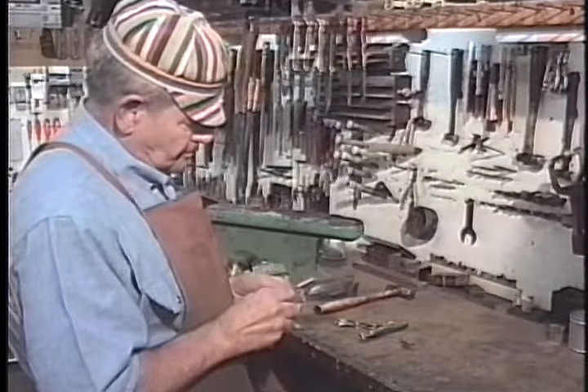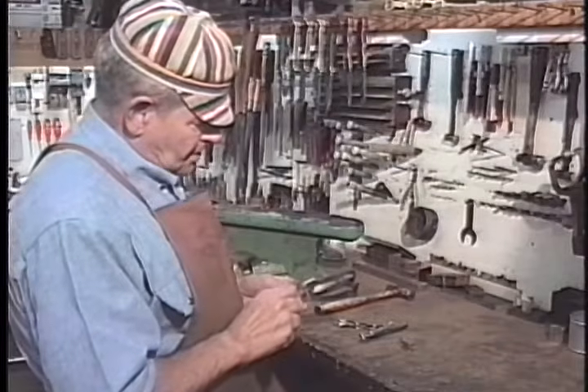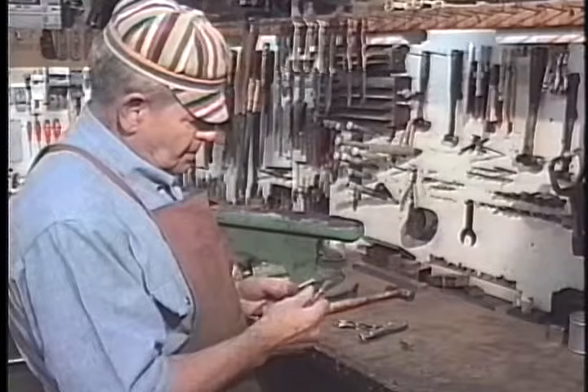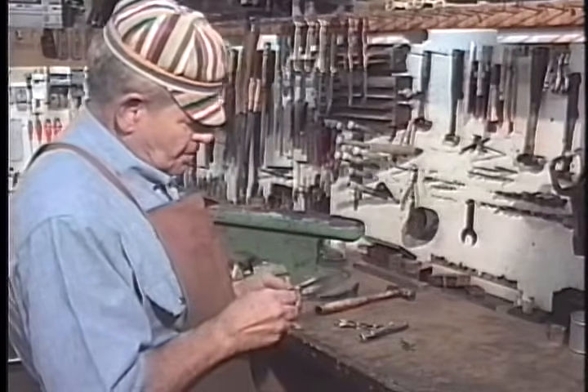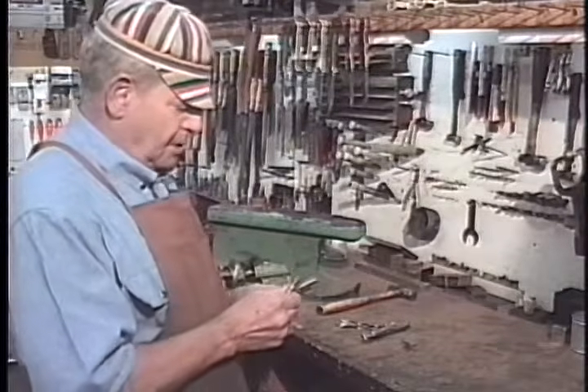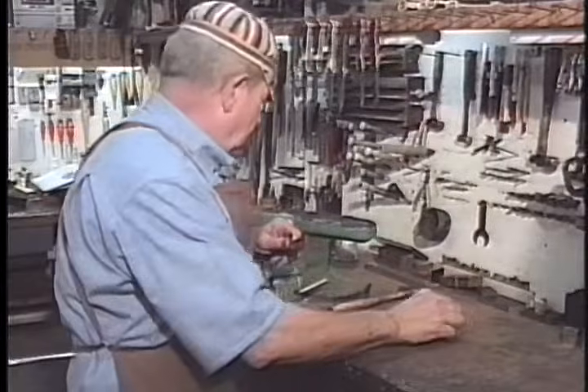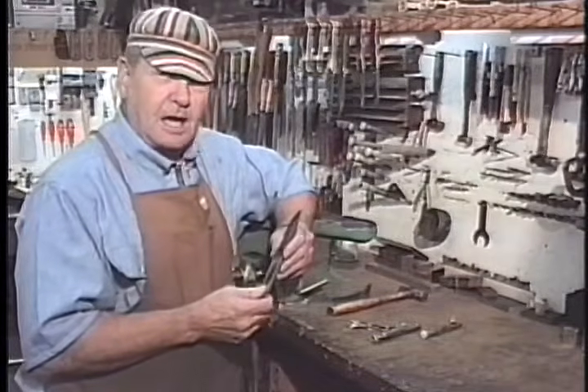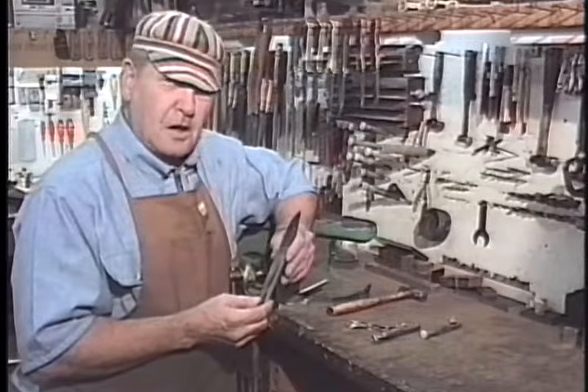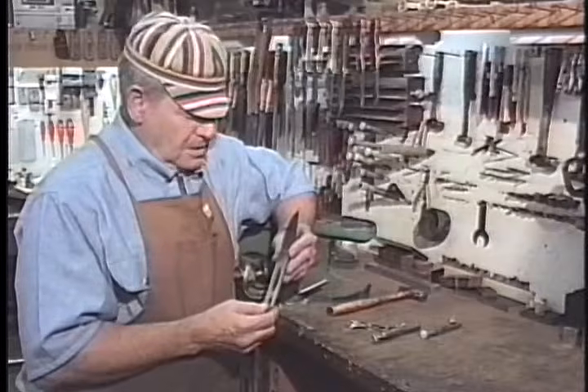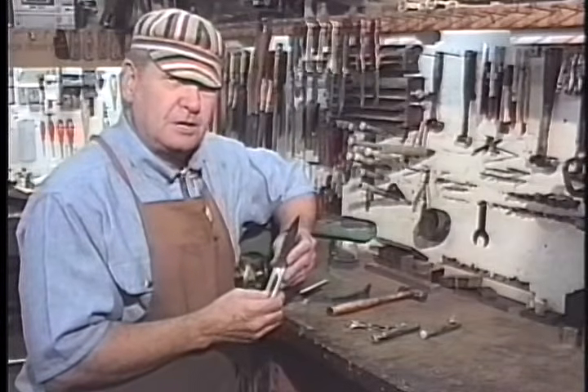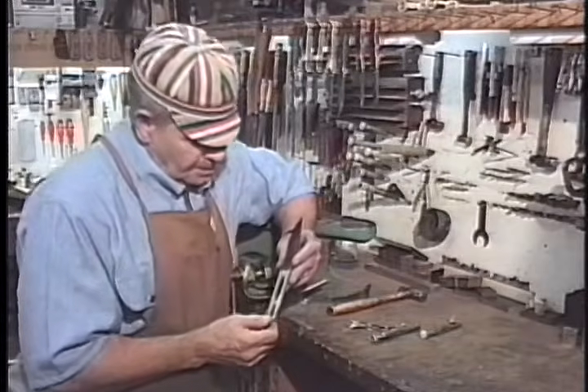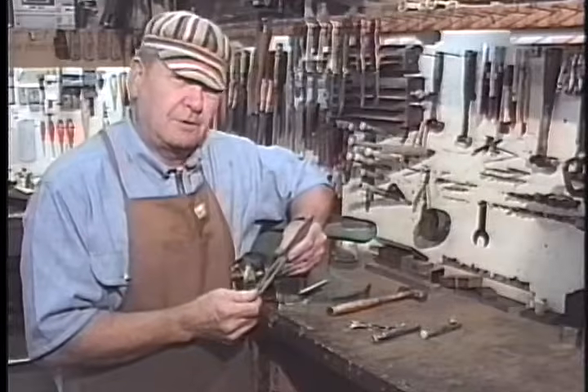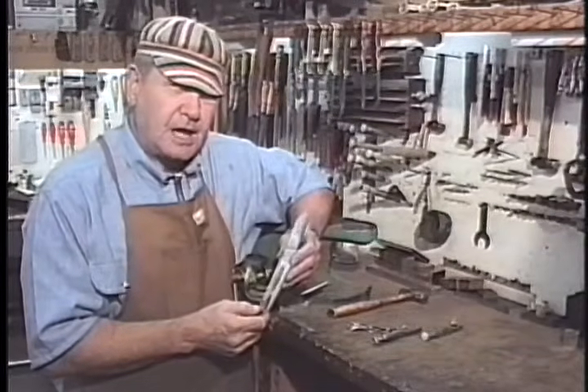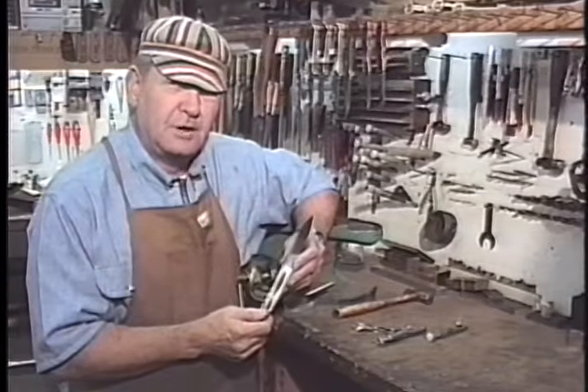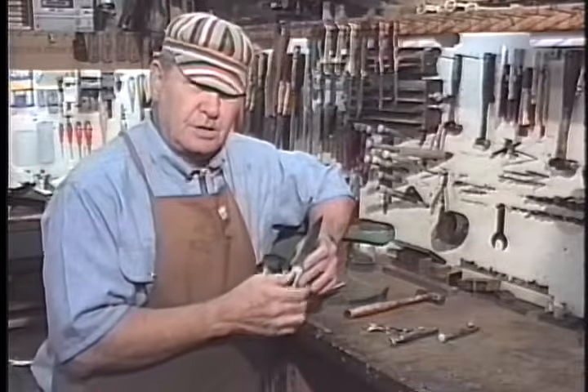Now, because this kind of steel is a fairly complex high carbon, high chrome, high manganese tool steel, it's not the sort of thing that you can stick in a microwave, nor can you put an acetylene torch on it and just bring it up red hot and dip it in the nearest can of motor oil. This is heat treated in what we call a gaseous furnace, where all the oxygen in the furnace chamber is purged so that steel can't decarburize while it's being brought up to heat. And it gets pretty hot. It has to be brought up to around 1975 degrees and held for something like 10 or 12 minutes, and then gas quenched, which simply means that the furnace suddenly has a great deal of nitrogen under pressure admitted to the furnace, and that quenches the steel and hardens it.